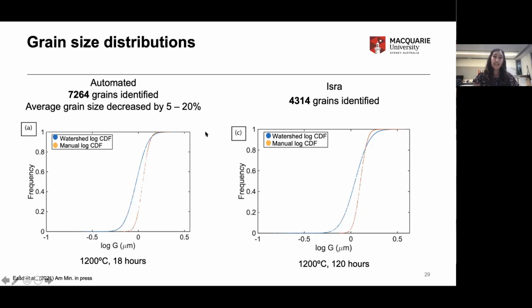What was really important, and actually a surprising result to me, was that the average grain size decreased by up to 5 to 20% from me identifying grains myself versus the automated approach. Interestingly, we also saw that the watershed approach has a much better ability to capture the entire distribution. You can see here in orange, this is my attempt at measuring grain size, and there are clearly missing grains throughout this distribution.